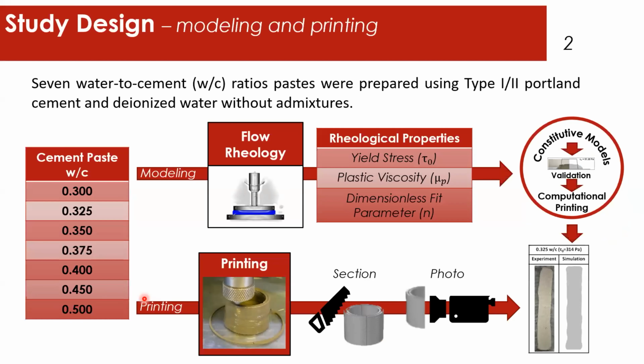Now, this work revolves around a particular experimental design where I have 7 water to cement ratios of cement paste, which are neat cement paste without any admixtures. So there are 2 pathways. There is a modeling path where I use experimental flow data to extract yield stress and plastic viscosity information that is needed for constitutive models. Then there is a separate validation step. I do computational printing and produce a computationally printed object that is compared to the second pathway, where I actually print the object, section it, photograph the cross section, and make the comparison between experimental and computationally printed objects.